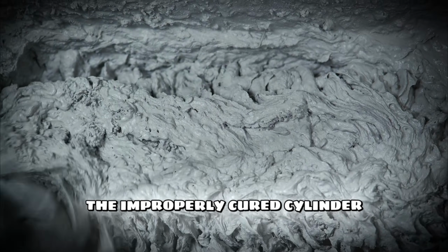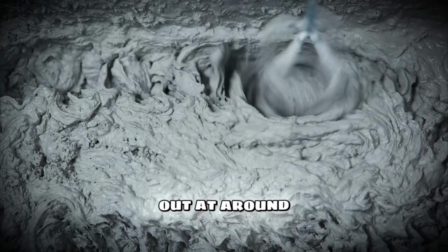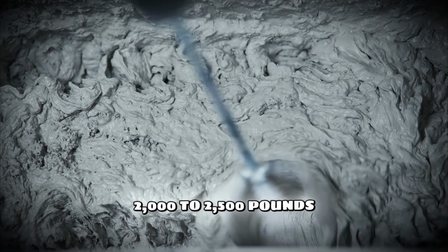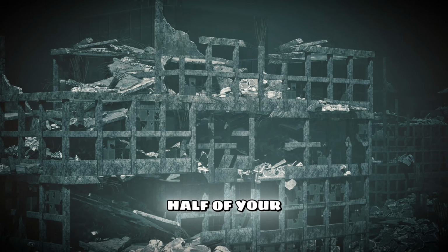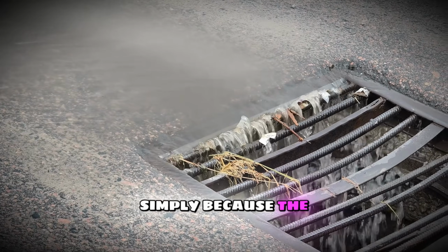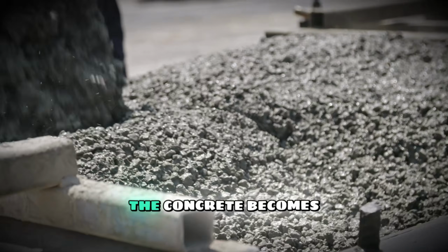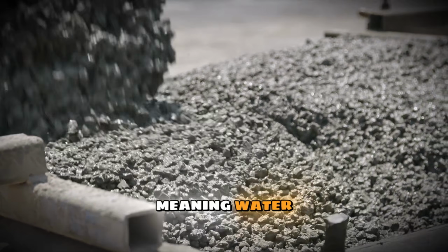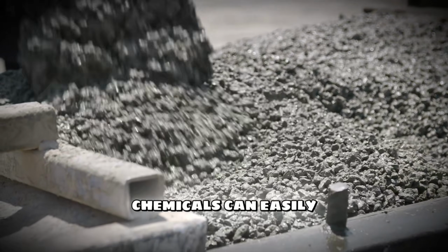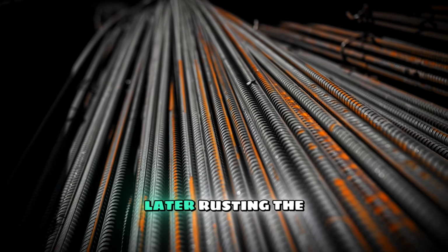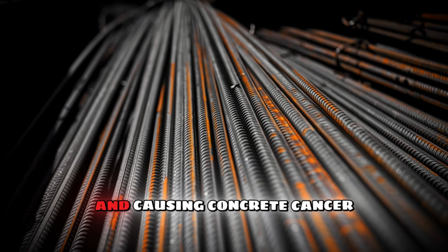The improperly cured cylinder will likely top out at around 2,000 to 2,500 pounds per square inch. You have lost half of your structural capacity simply because the water evaporated too fast. The concrete becomes highly permeable, meaning water, road salts, and chemicals can easily penetrate it later, rusting the internal steel rebar and causing concrete cancer.